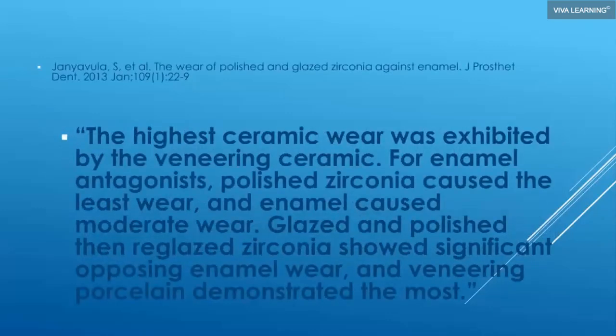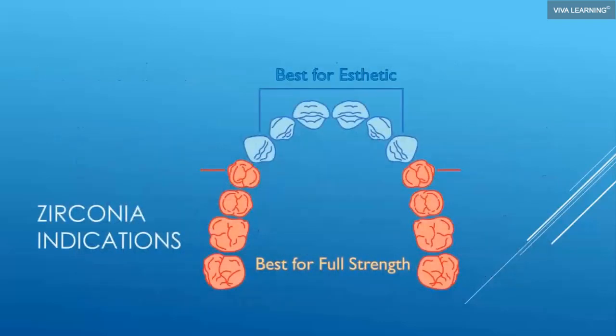And the highest ceramic wear was exhibited by the veneering ceramic. For enamel antagonist, polished, and this is important, polished zirconia caused the least wear, and enamel caused moderate wear. Glazed and polished zirconia showed significant opposing enamel wear, and veneering porcelain demonstrated the most. So between reglazing or glazing zirconia and veneering porcelain, that's where you have your highest wear. So you must tell your laboratories, do not glaze my zirconia. Hand finish or hand polish my zirconia.